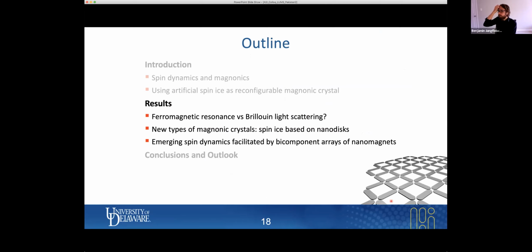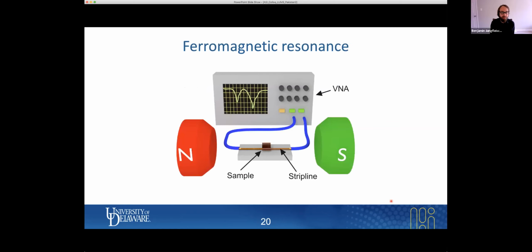So now let me jump into the results that I would like to present today. First, I'm going to show you a comparative study between ferromagnetic resonance and Brillouin light scattering in a square lattice. So ferromagnetic resonance is pretty simple. You have a device called a vector network analyzer. You send a microwave signal from one port into an antenna, you excite dynamics and basically measure the absorbed energy by measuring the transmitted signal. When you're in resonance, you excite the magnetization dynamics, and therefore you have a loss of the microwave signal, and you can do this as a function of field.